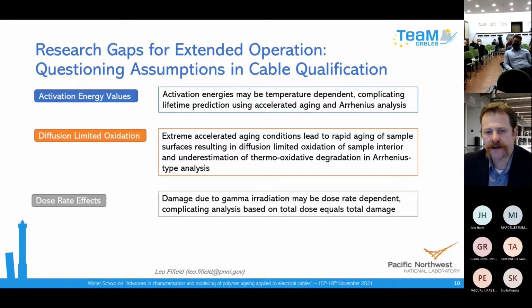And you can actually underestimate the effect of that aging because the interior of the polymer sample is actually protected by that rapidly aged exterior. I kind of think of it like aluminum: you cut a fresh surface of aluminum and it reacts very rapidly to make an oxidation layer, and then the rest of the solid doesn't oxidize because of that protective layer on the outside. I think of it as a similar process.